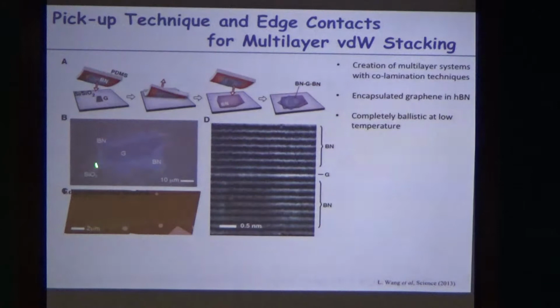In this particular example, graphene encapsulated in between boron nitride can be made or synthesized in such a way, right? In the proper condition you get a few tens of microns, or at least a few microns, of crystal area that is extremely clean. And if you cut it through and look at the cross-sectional TEM image, you can see that this atomic interface is extremely clean, indicating that we can in principle make these materials or heterostructures one by one by design.